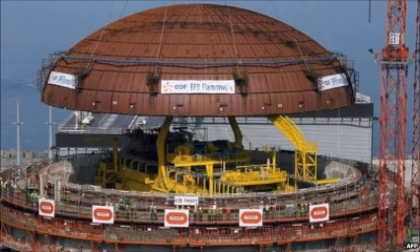In a joint statement, Areva and EDF said new tests were underway on the reactor vessel head and bottom. It said this followed initial tests which had shown greater than average carbon content, something French regulators said caused lower than expected mechanical toughness in the steel.